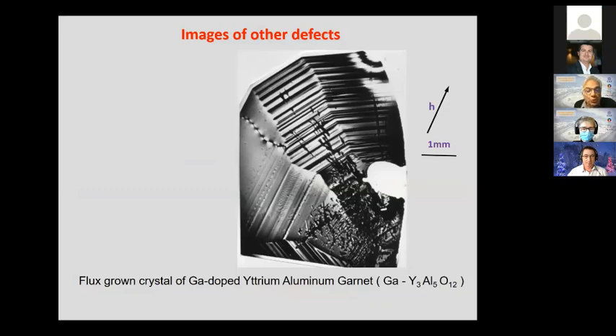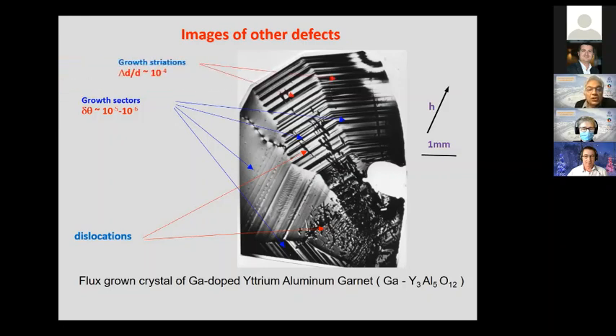Let's look at other defects with an image of a flux grown crystal of gallium-doped yttrium aluminum garnet produced for applications. You can see a lot of things there. For instance, dislocations, which are these lines like before, but also growth sectors, which correspond to the different facets growing from the seed during the growing process, and also growth striations, which correspond to fluctuations in the growth temperature or composition fluctuations. You can also see magnetic domains and even an inception of a crack with a beautiful contrast here.